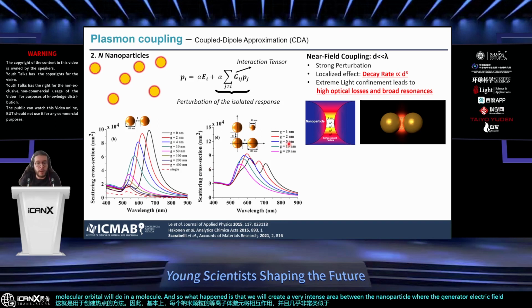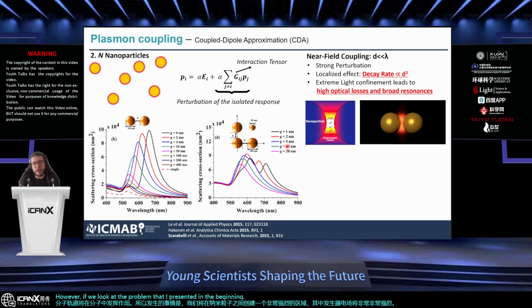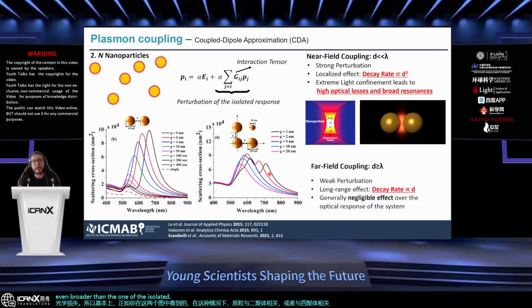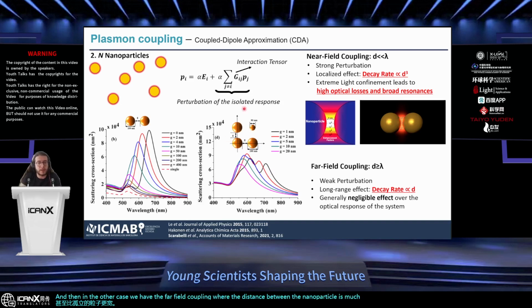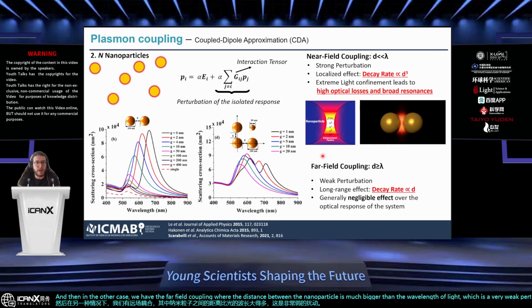However, if we look at the problem that I presented at the beginning, the fact that these systems have very high optical losses, this is actually a source of optical losses. As you can see in both graphs down here in these two plots, the plasmon associated with the dimer in this case, or with the tetramer in this other, are even broader than that of the isolated particle. In the other case, we have far-field coupling, where the distance between the nanoparticles is much bigger than the wavelength of light, which is a very weak perturbation, and we generally consider this a negligible effect. So we treat particles that interact in the far field as basically isolated particles.